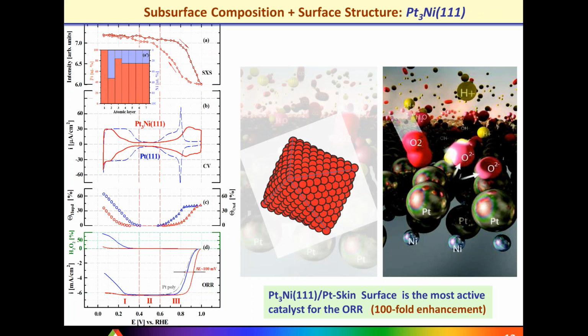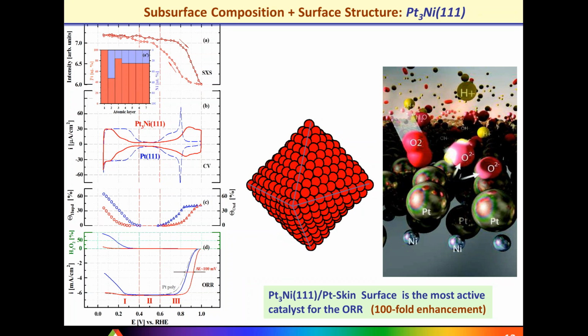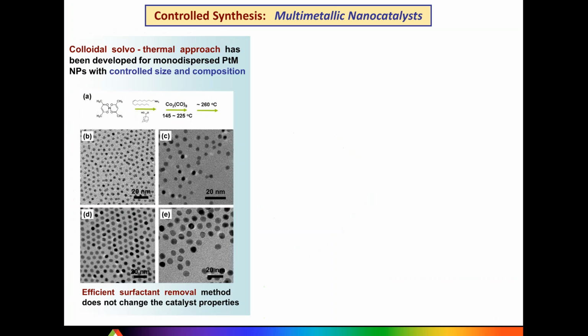So based on that, we can learn and we can collect design rules for the ultimate catalyst, which our hope was to make something like an ideal octahedron where only platinum atoms are going to be exposed while nickel is going to be in the subsurface, and to get there is extremely challenging. So in order to pursue something which is a so-called rational approach, we need to have all of those parameters under control. And as I introduced in the beginning, the first of them is actually to make sure that we have very good control of particle size. So how to get there into particle size control, shape control, and compositional profile control, it's really extremely challenging if we are targeting to control all of them.